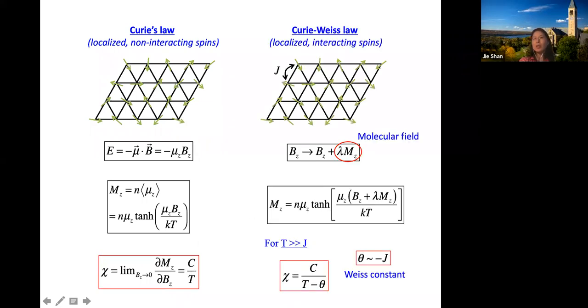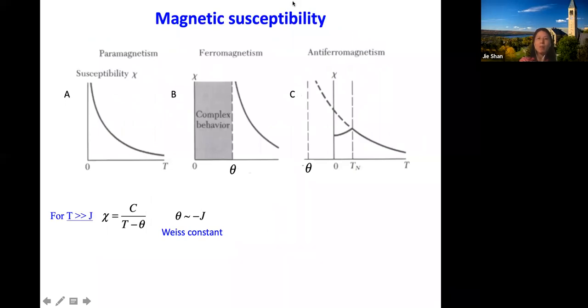Now if we include the interaction energy, on the order of J, this picture can be modified. The field that each localized spin feels is not just the applied magnetic field, it also has the field that comes from the other spins. This is called the molecular field, or sometimes the Weiss field. If you take this into account, you can modify the magnetization as a function of temperature and come up with the Curie-Weiss law. Susceptibility goes like a constant divided by T minus some Weiss constant, which is on the order of this magnetic interaction J.